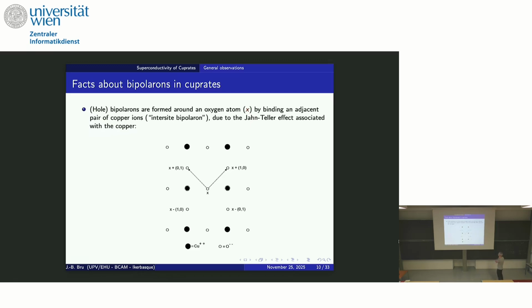And so that's what happened. In fact, there is a formation of polarons, as they found experimentally. And there is one additional thing: it's antiferromagnetic, and they showed in experiments that there is still antiferromagnetic correlation even if the antiferromagnetic phase disappears. If you have a polaron with only spin up, it's difficult to move, and it turns out to be favorable to get a bipolaron. So two polarons are created at the same time, with spin up and spin down, which is well adapted to an antiferromagnetic correlation because they are up and down.